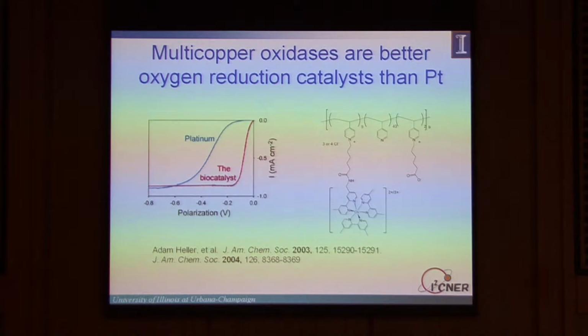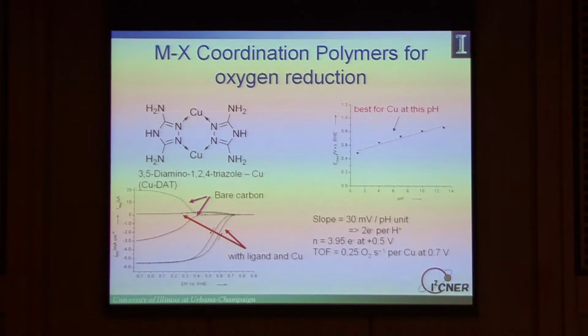The interesting thing about this is that many people have shown that this catalytic material is substantially better than platinum. And so all we have to do is figure out how nature did it, and then we are better than platinum, and we solve this problem. We've done some of that. We have a material based on this 3,5-diamino-1,2,4-triazole right here, which forms a binuclear copper site. We've shown that this catalyst is the best catalyst for copper at intermediate and higher pHs right here. And we've been spending a lot of time working on that.